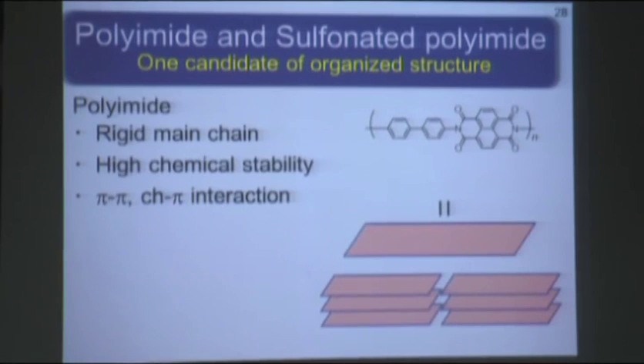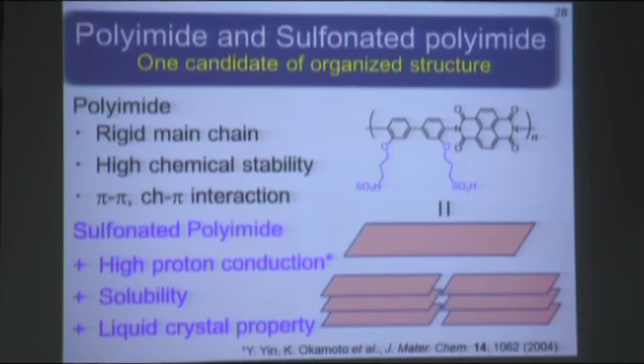Okay, by using this concept, let me introduce the polyimide. What is polyimide? Polyimide like this. The characteristic is a rigid main chain, very rigid, and high chemical stability, applicable to industry, and also the pi-pi interaction. So this is like aromatic, many aromatic rings, so that this is like a rod structure, easy to assemble like this. By introducing the sulfonic acid group as a side chain, yes, this gives high proton conduction. This is already known, not our work. But the structure is totally unknown. So we found that the solubilities are also improved so that we can make any shape, and the liquid crystal property of that.